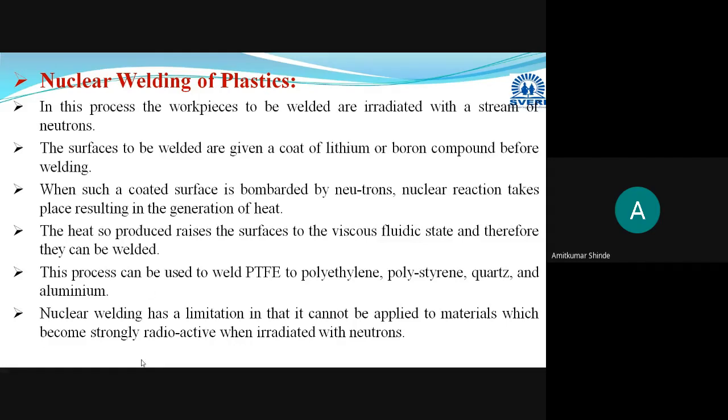Another limitation is that nuclear welding cannot be applied to a material which becomes strongly radioactive when it comes in contact with the neutrons. For those particular materials we cannot use this method, and you have to control the flow of neutrons also. Otherwise, if more flow of neutrons occurs, that material loses its strength and will become brittle in nature. So this is the nuclear welding of the plastics.